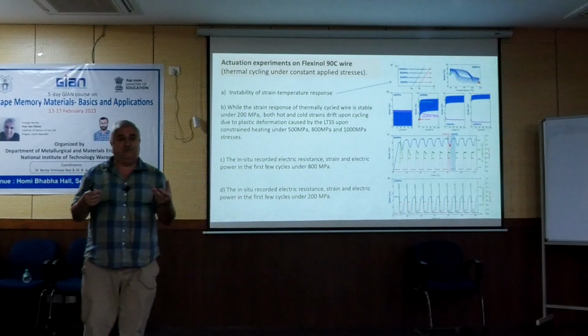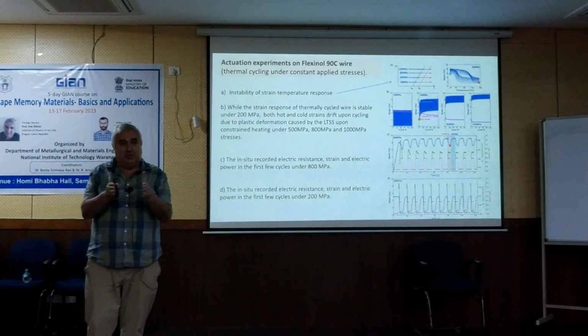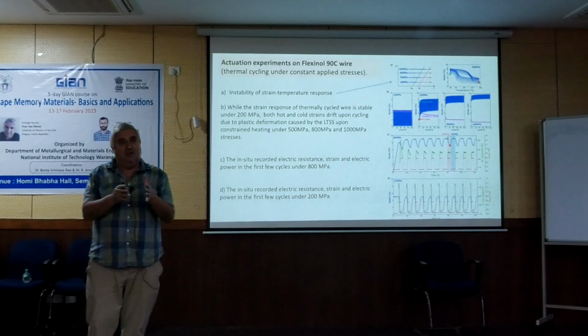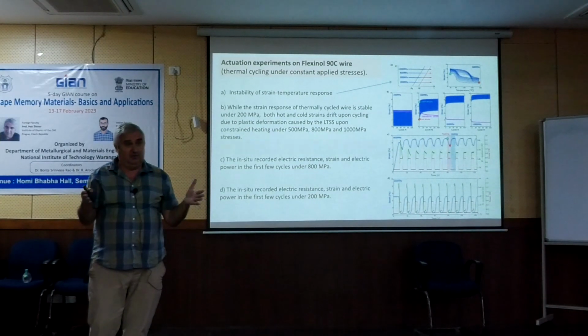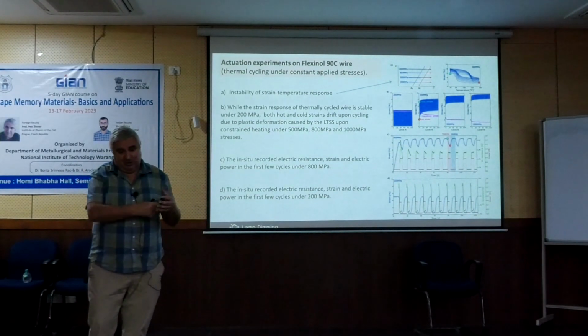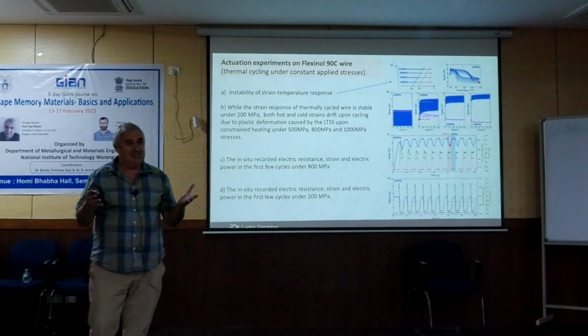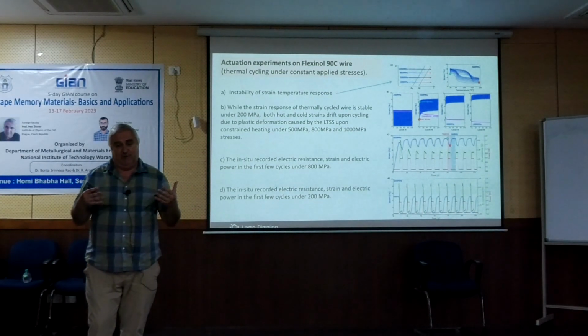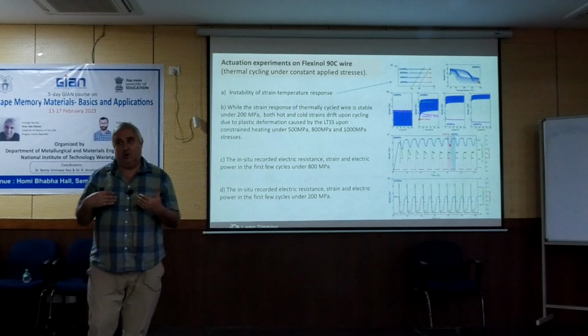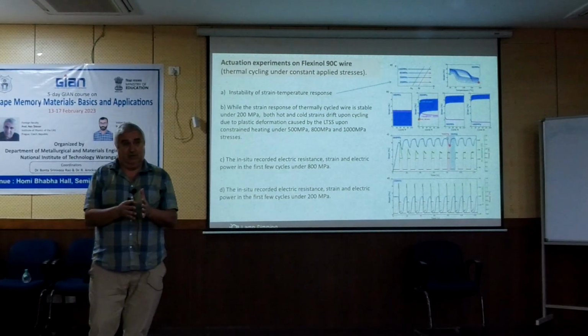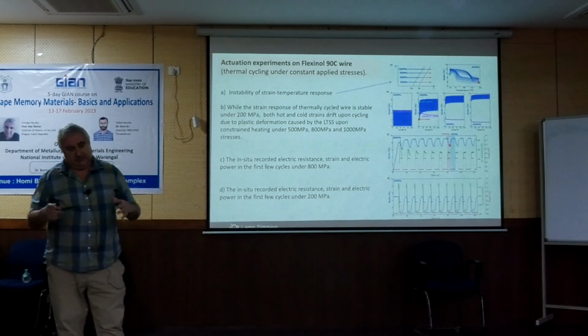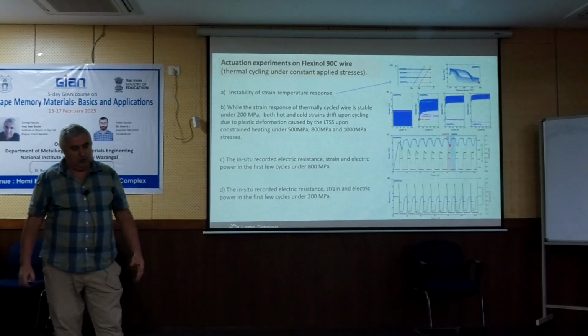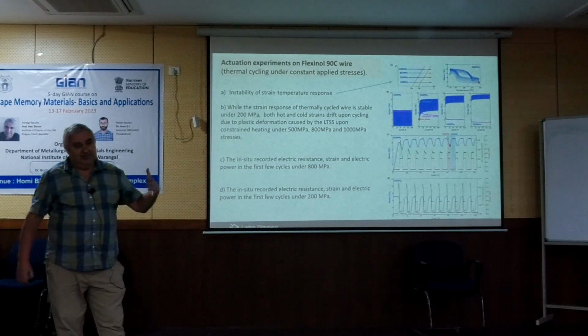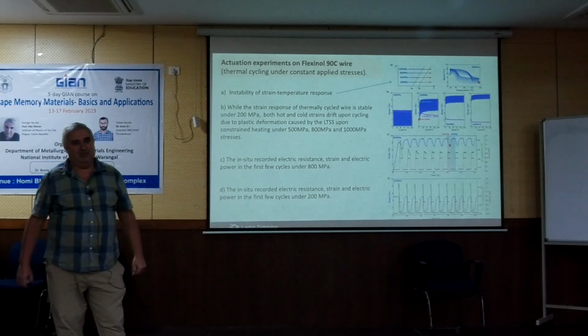So the successful demonstrators now use the shape memory tubes in compression. So if you have tube and deform it in compression, it will not fracture. You can go to millions of cycles, and you can have easily water flowing through the tubes, and you have a big surface. So these demonstrators of elastocaloric cooling, as far as I know, are using the tubes in compression, and they make the tubes by 3D printing. So it's in a shape with multiple tubes. So elastocaloric cooling is definitely the area which seems to be promising. But it requires a bit time to get into this field. It's not straight away.